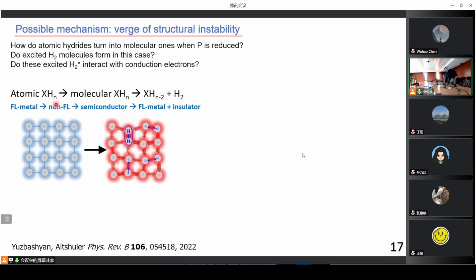We can propose a very simple, primitive mechanism: firstly, the atomic hydride goes to a molecular phase. After this, the molecular phase decomposes to a lower hydride with emission of hydrogen, an insulating phase. So it passes via a non-Fermi liquid phase, after that a semiconducting phase, and after that the decomposition again leads to a Fermi-liquid metal, but with lower Tc and an insulating phase of hydrogen. In this case, some phonons in the hydrogen sublattice may lead to strong interaction between two neighboring hydrogen.